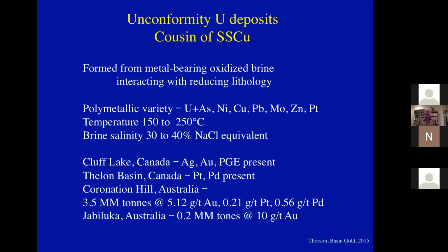There is a polymetallic variety that contains uranium plus arsenic plus nickel, copper, lead, moly, zinc, and platinum. The temperature of the unconformity uranium deposits is generally thought to be between 150 and 250 degrees centigrade. The brine salinities are very high, with 30 to 40% NaCl equivalent in the fluid inclusions from the brines that deposited these metals. Now, in the western part of the Athabasca Basin at Cluff Lake, there's known to be silver, gold, and PGEs in the unconformity deposits there.